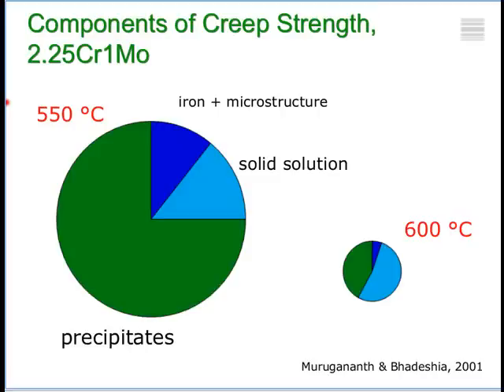Notice that the contribution from precipitates at 550 degrees C is very large. But it becomes very small when you get to 600 degrees centigrade because the precipitates become large and the spacing between the particles increases. And furthermore, defects can avoid the particles by diffusing over the defects. Okay? So here, the contribution from precipitates is very small compared with this. But solid solution strengthening doesn't change with temperature. So you have a large amount of solid solution strengthening.